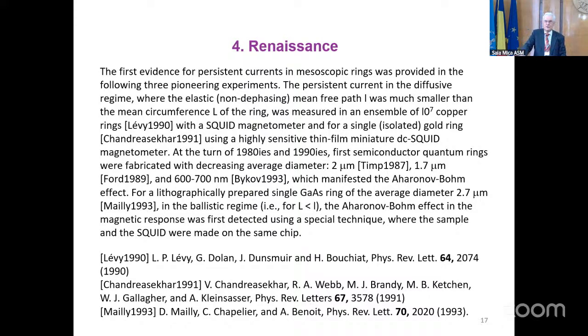And he made something which really admired the community at that time. He made not only a ring, but also a SQUID in the same structure. So he grew in one run both the quantum ring and the SQUID which was intended to measure the magnetization. Otherwise, it would be very, very challenging, if at all possible, to measure. And when he did it, it was really a long time of work. He observed in the ballistic regime the Aharonov-Bohm effect in the magnetic response, which was a fast detection of the Aharonov-Bohm effect with this special technique.